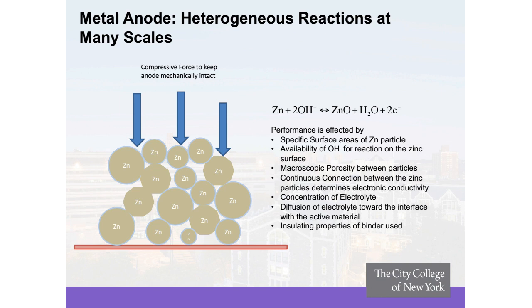How do we compensate for that is by using either compressive forces to keep the particles always in contact with one another, by the stack pressure that is applied into the actual battery, or by using binders that allow the material to stay together. However, these are not efficient, and they actually provide other problems.